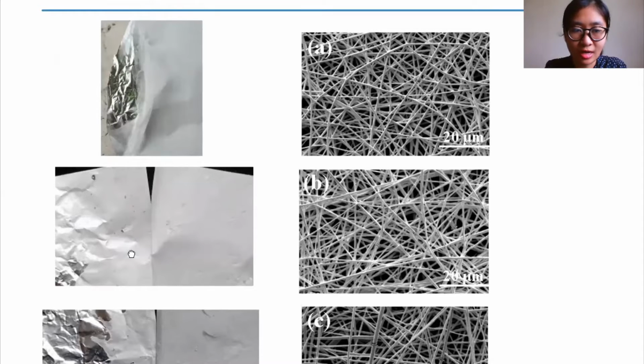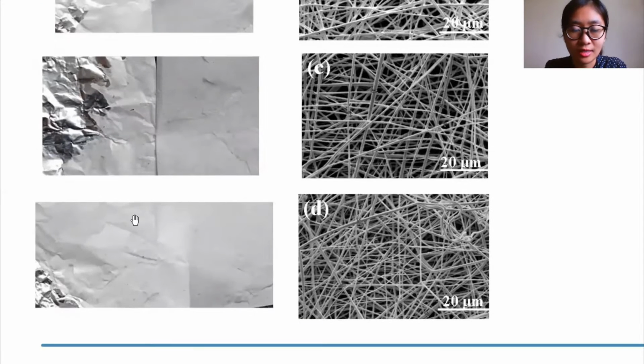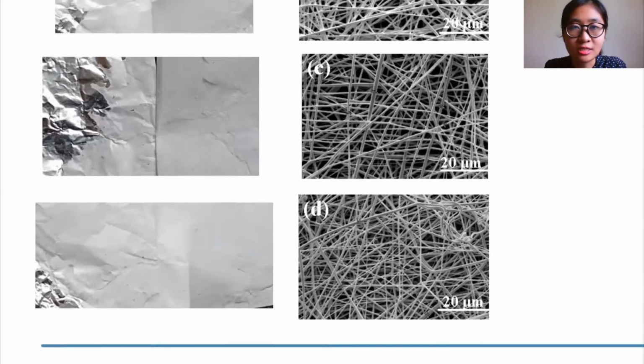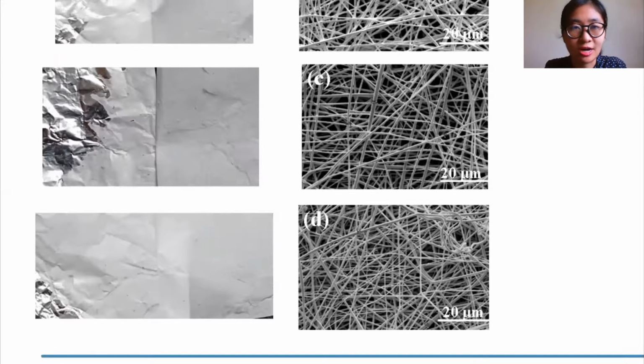And as you can see, they are not peeled off totally from the foil, maybe because of its thinness, or a plausible explanation would be because of the electric charge between the foil and the fiber mats, which keeps the fiber mats attached to the foil. Remember, this was initially a solution that has been electrically charged and traveled as a jet from the needle to the collector plate with the aluminum foil. Okay? Also, electrospinning this for about 4 hours or less only produces about 0.07 to 0.11 millimeter thick, which is considered very thin. Okay?